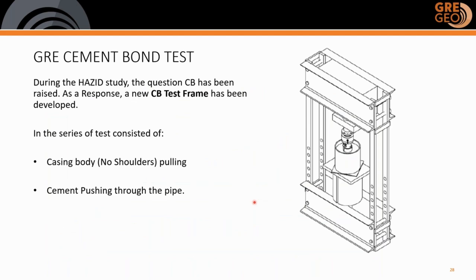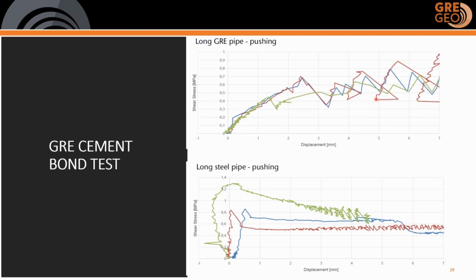Then we moved to the cement bond test. We made a separate setup for that one, and we tested both internal and external cement bonding, and tried to push the cement through the pipe, or the pipe through the surrounding cement. We may see here that the overall performance is a bit lower than in the case of steel, because we have a very big force requirement to push it through compared to the GRE pipe. However, the subsequent movement of the pipe within the cement will then be obstructed, which is not the case with the steel. Overall, the difference was around 30% less force needed for the GRE. And that is not a very big difference in the case of the cemented casing string.